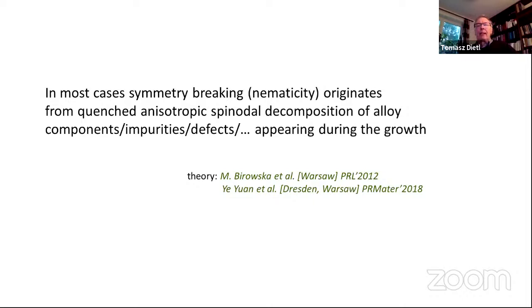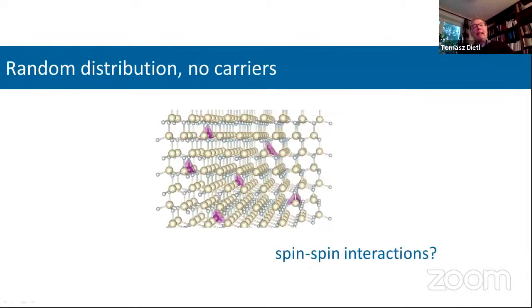And the physics is associated, as we discussed with the theoretical paper, and demonstrated, with the fact that the growth surface usually has lower symmetry than the bulk, and this quenched anisotropic spinodal decomposition actually begins during growth at the growth surface, which, as I said, has lower symmetry than the bulk of the system. Then you see in the bulk also this pattern, which is at the surface. Okay, but in some cases, actually, we can manage to have random distribution.